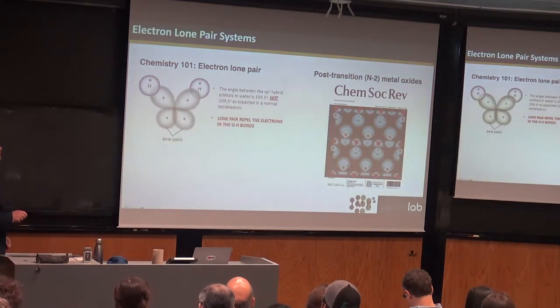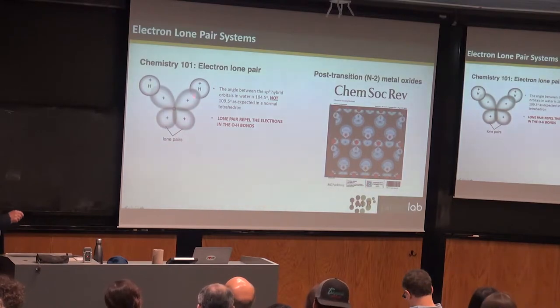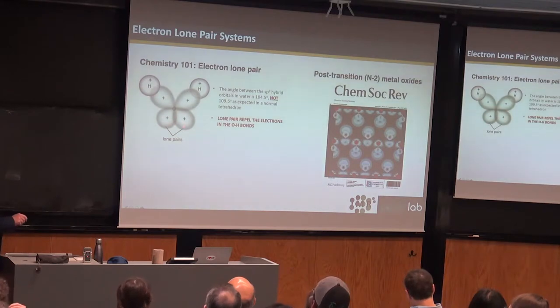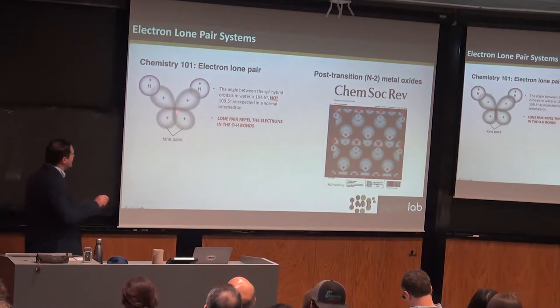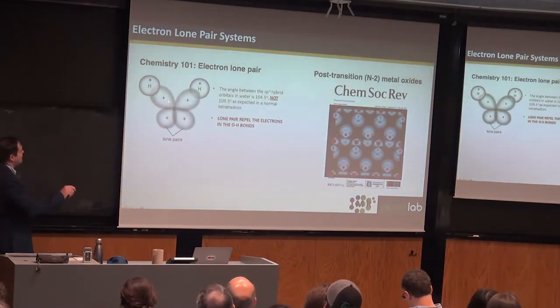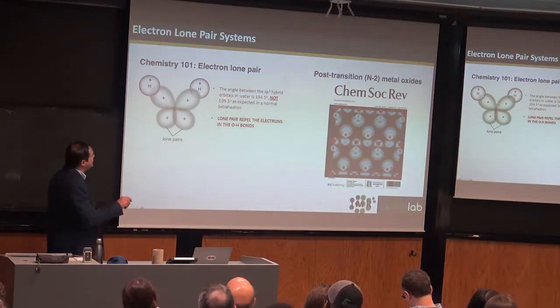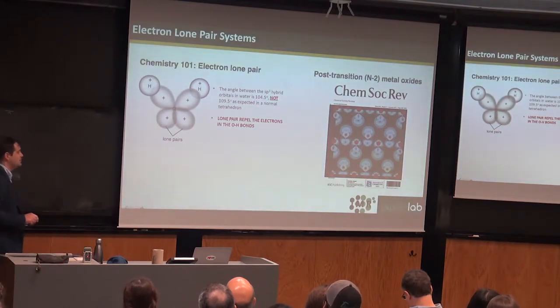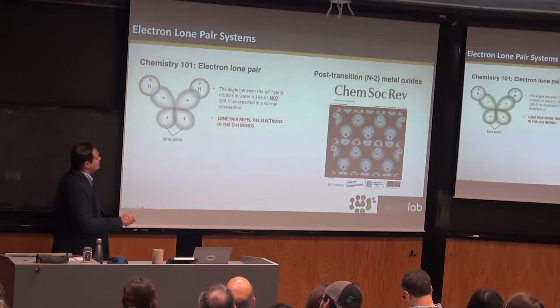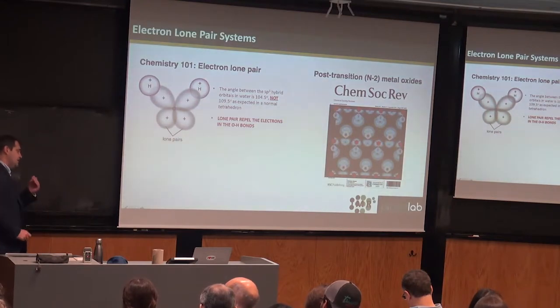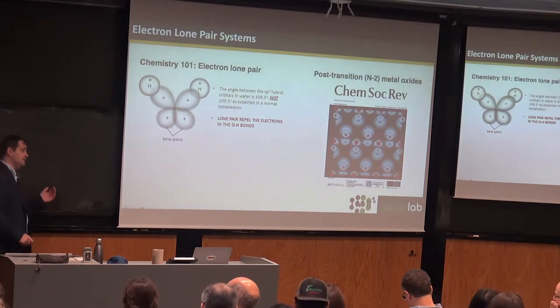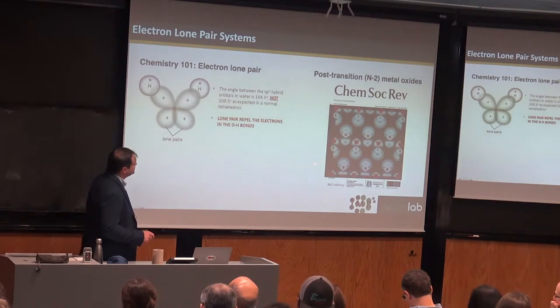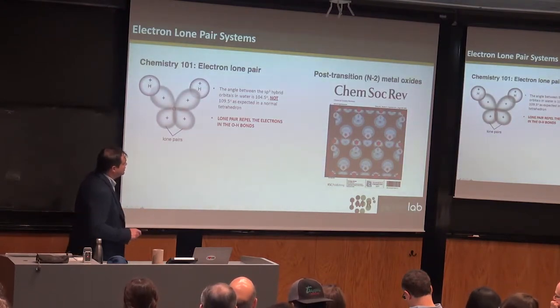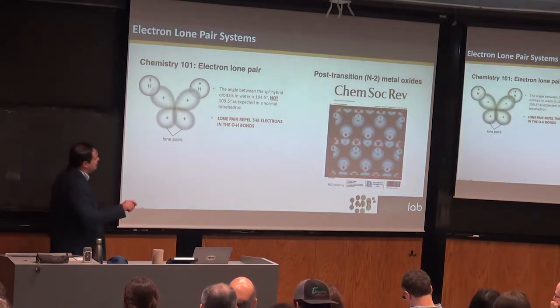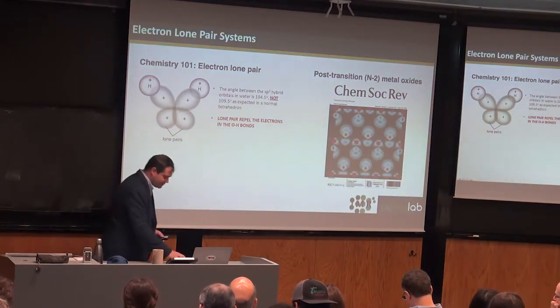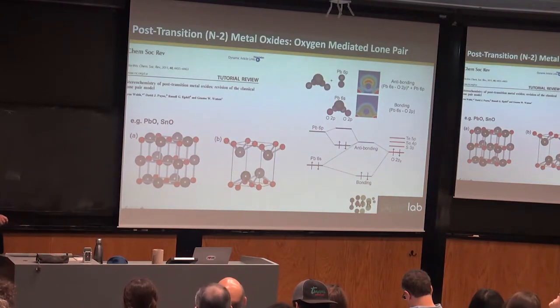So, as I said, not a chemist, but chemistry 101, if we look at the water molecule, we know that there's bond pairs and lone pairs, and the lone pairs are essentially ones that don't reflect bonding, and as a result, they take up more volume, and you have a case where you have a distortion of your bond angles because of it, and so this is why your bond angle is not as you would expect just from pure symmetry. But what I'm going to be talking about is post-transition ns2, in that case you're taking lead, but not using the more stable 4+, you're using the 2+ ion, the less stable, so the tin and bismuth 3+ instead of bismuth 5+. And in those cases, you still form a lone pair that leads to these structural distortions, but the origin of the description of these is slightly different, because they do have to explicitly consider hybridization with the anion.